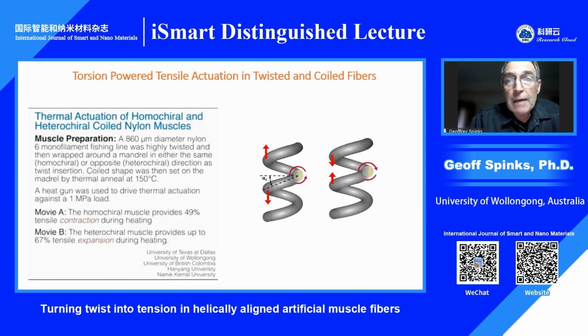So if you take the same twisted fibre and now fabricate it into a coil, we hypothesized that instead of seeing a rotation, you would now see the coil length change. In other words, we could change a torsional actuation into a tensile actuation. And we proposed an experiment to prove this correlation, and that was to take a twisted fibre, twist it in a certain direction, and then fabricate it into two coils. One we called homochiral, which is where the twist direction and the coiling direction are the same. And then separately, another coil where the twist direction and the coiling direction were opposite. And we called that a heterochiral coil.